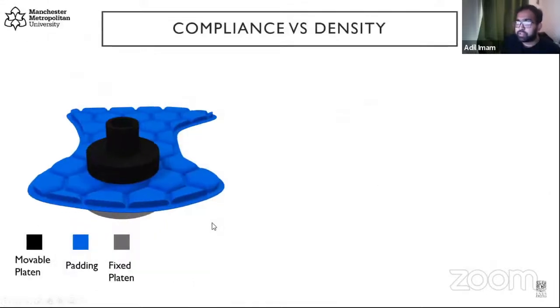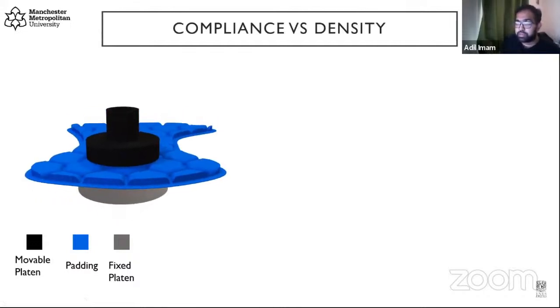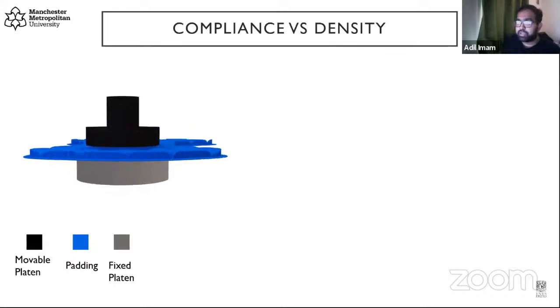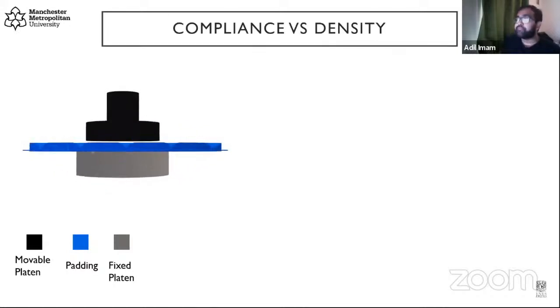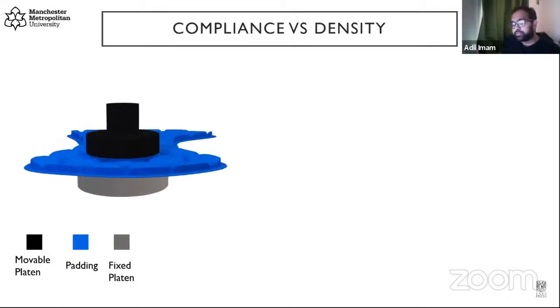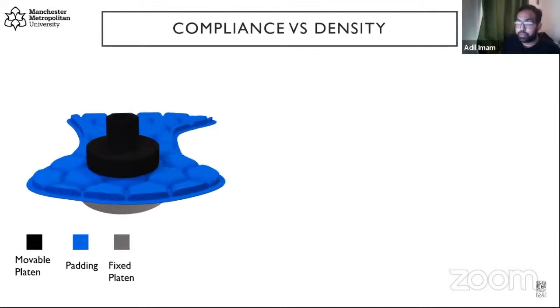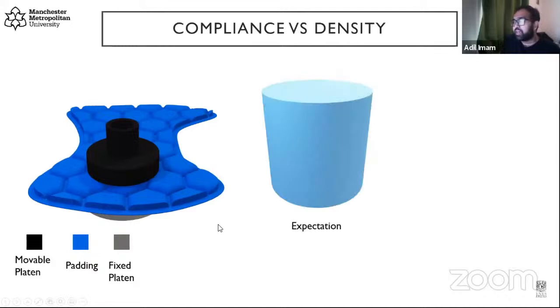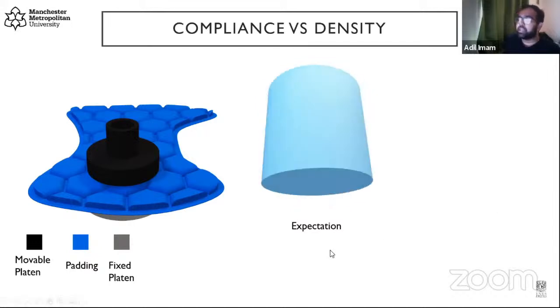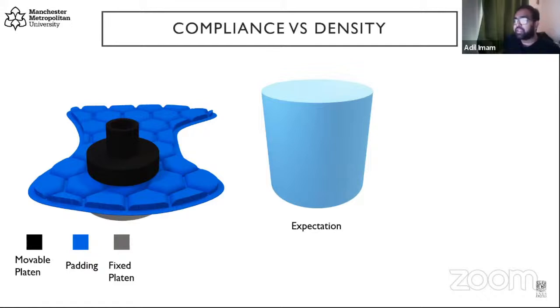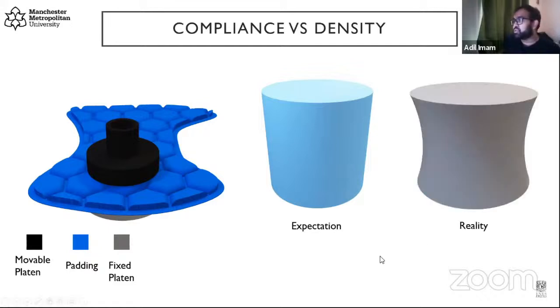Now, we carried out simple compliance testing where we compressed the padding using two flat plates to look at how compliant the material is or how soft or stiff the material might be. And then we carried out some density testing by cutting out paddings from the given padding we have. And you expect to get uniform circular cylindrical structures, which you could calculate the weight, the mass and the volume and get the density of. But in reality, you get structures which are warped cylinders, and measuring them leads to error in your density calculations and, you know, higher error in measuring the final density of the material.